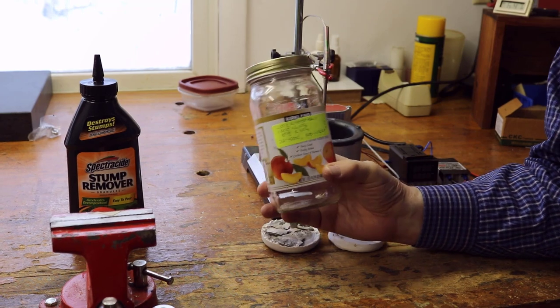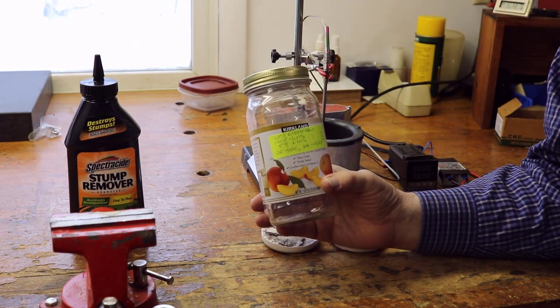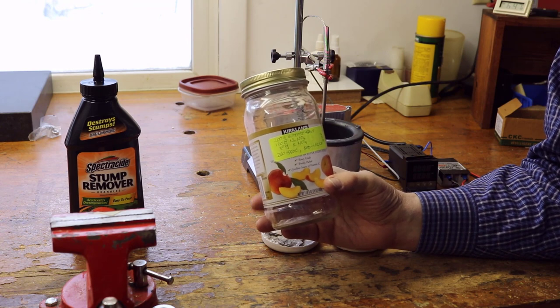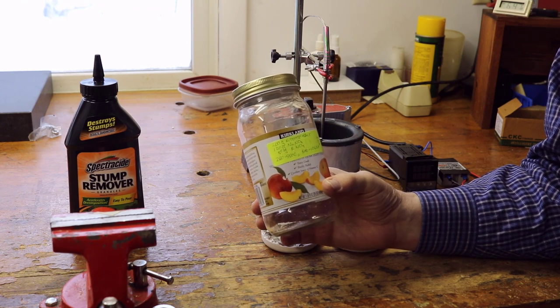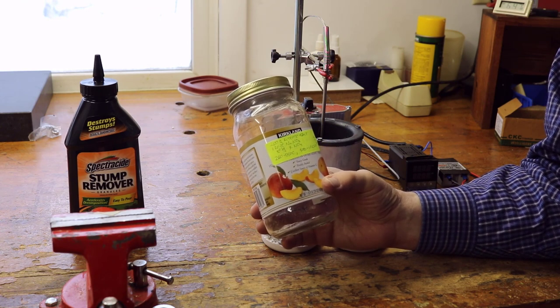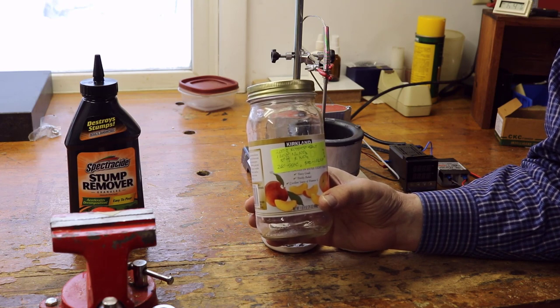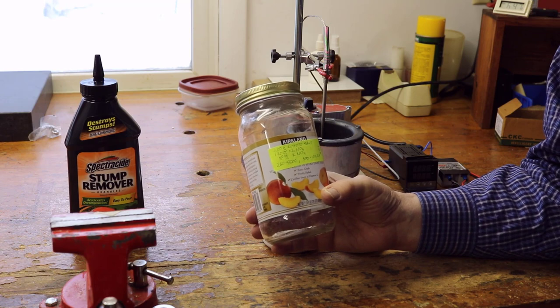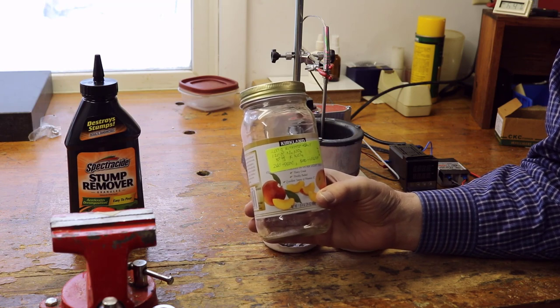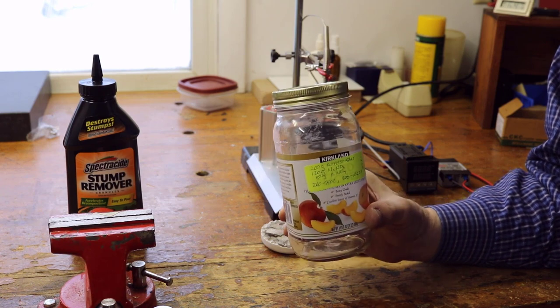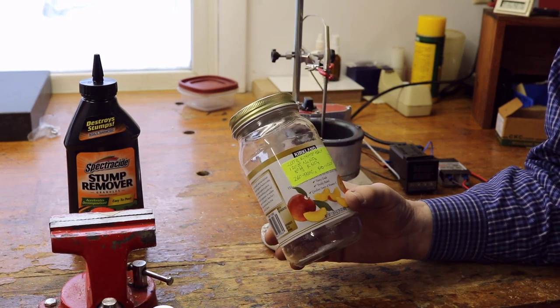Now some of you saw this earlier on, this is my bottle that I mixed up my supplies in, and this was a mistake. You shouldn't mix those up in advance. You should mix what you need, because if you don't, what happens is that the granules separate in the jar and your mix won't remain the same.